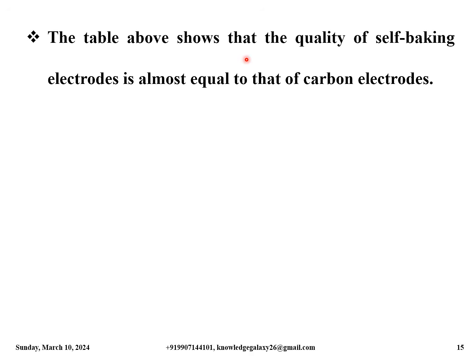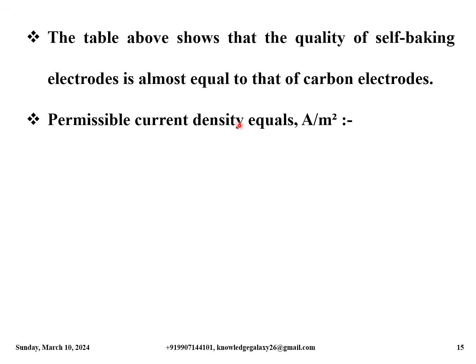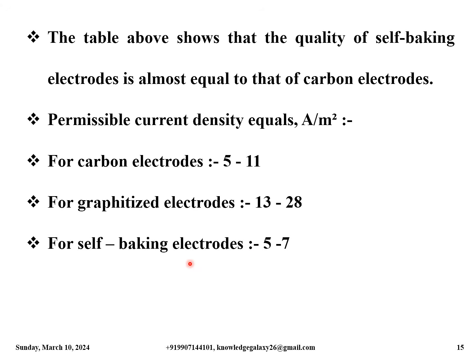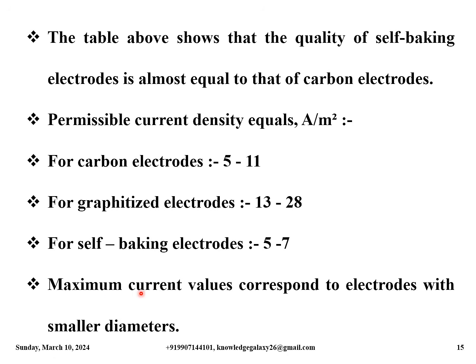The table above shows that the quality of self-baking electrodes is almost equal to that of carbon electrodes. Permissible current density is in amperes per square meter. For carbon electrode it is 5 to 11 amperes per square meter. For graphitized electrodes it is 13 to 28 amperes per square meter, and for self-baking electrodes it is 5 to 7 amperes per square meter. Maximum current values correspond to electrodes with smaller diameters.